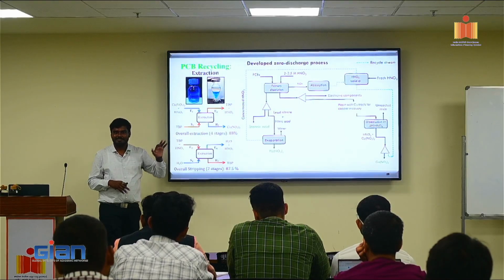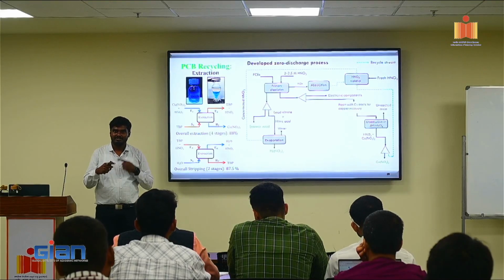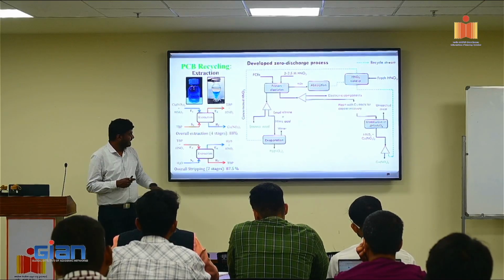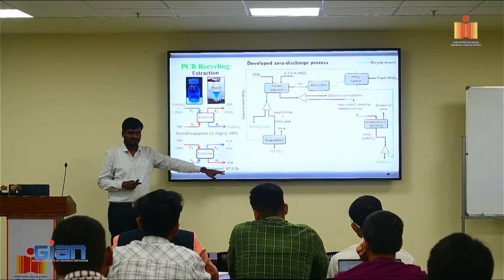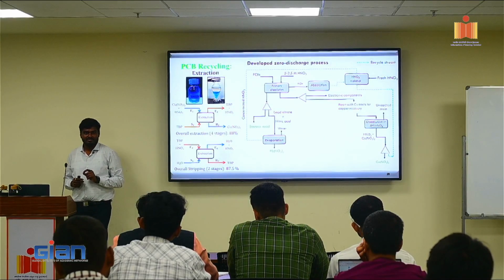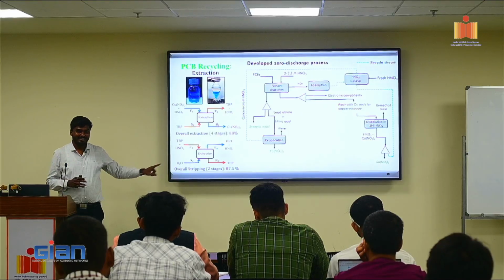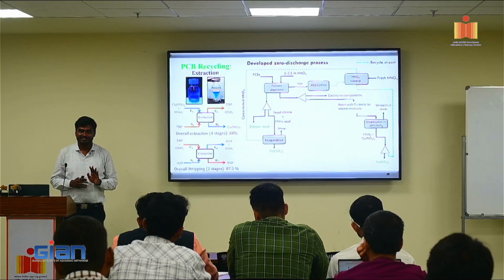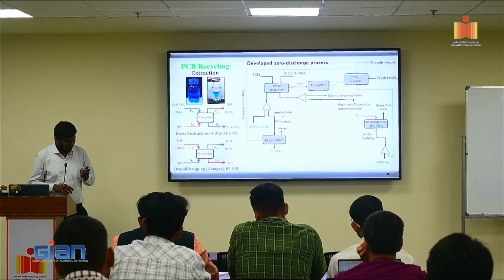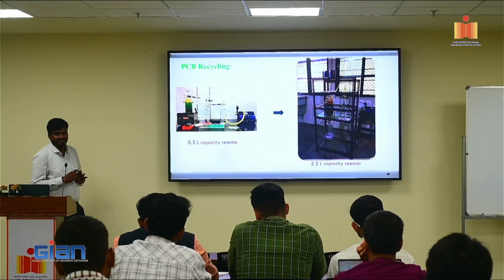So I did experiments for almost 8 to 9 cycles. I was using the same TBP and its efficiency never went down below 87%. So that's the one good thing that we found. It's not 100% efficient, but it's more than 85% efficient, which was good enough for scale up. So once we had, so this is the setup I had in lab scale.